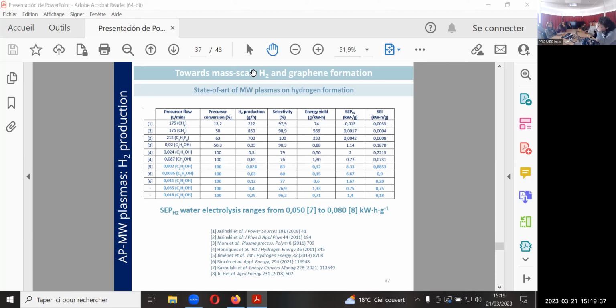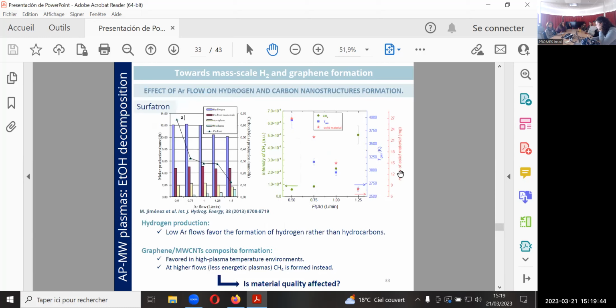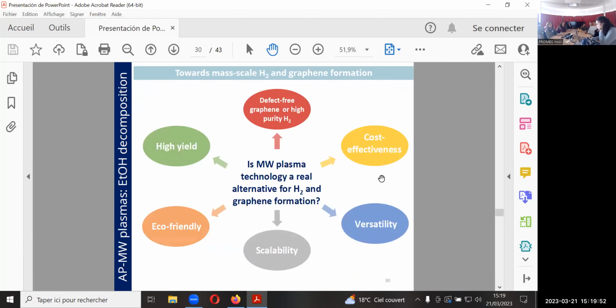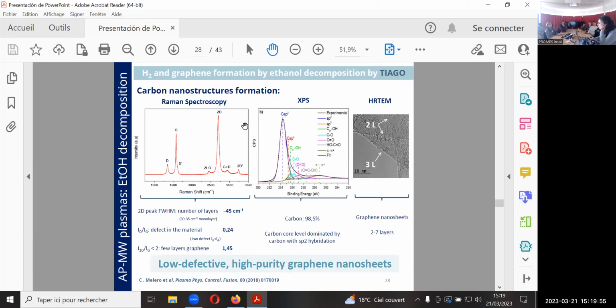Yes, when we analyzed our graphene by XPS, we decomposed the carbon peak, and what we observe is that the core level is mainly dominated by sp2, and only a small percentage of sp3 was found, which is actually in agreement with the low number of defects in Raman. So yeah, but it's something strange.